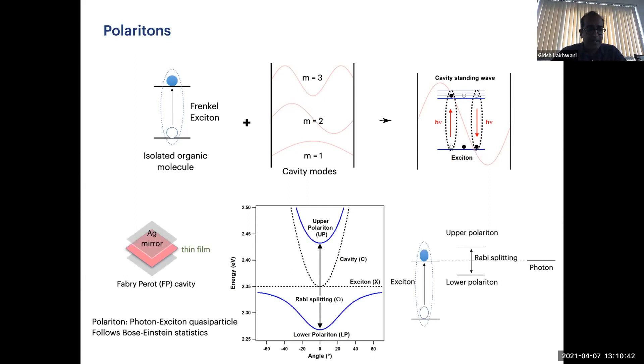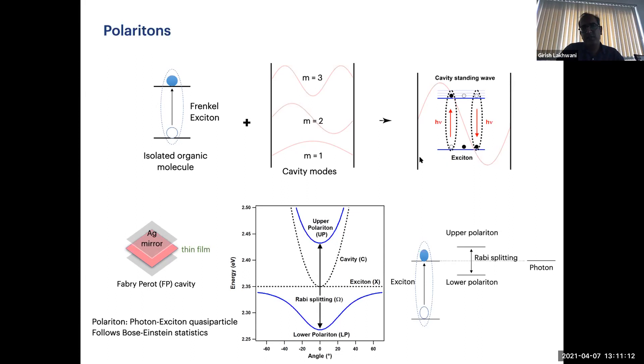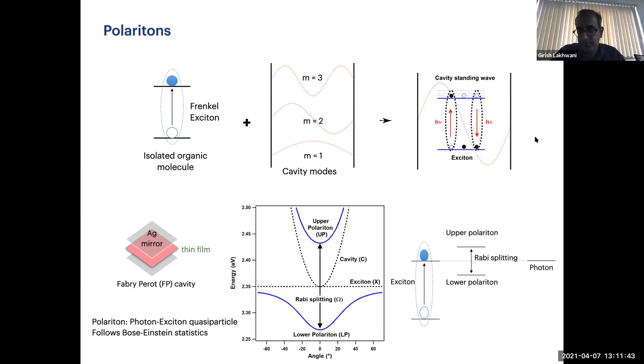Typically we study this by taking silver mirrors and putting a thin film between them — the thin film is made up of molecules. We want these molecules to be separated from each other to reduce thermalization issues or any other loss mechanism. If a cavity is leaky, you cannot support a standing wave properly. If the molecular exciton is aggregated, you will see thermalization issues, absorption and emission events will not be synchronized, and you will lose phase characteristics. So you want to minimize thermalization and have a good cavity that can support a stationary wave for a relatively longer time.